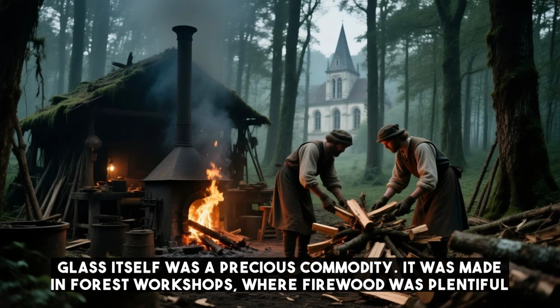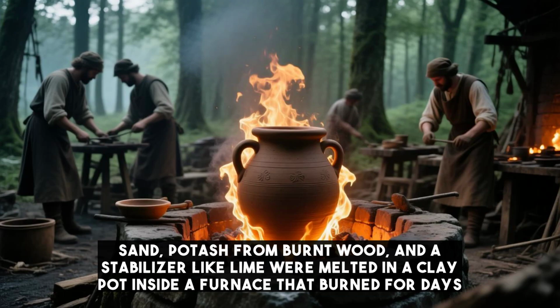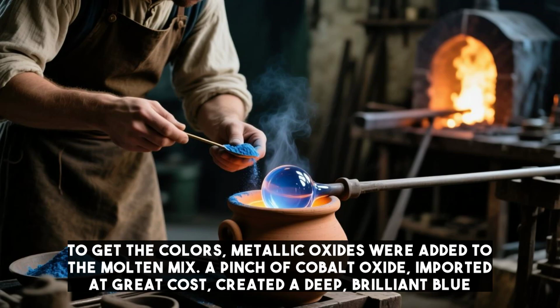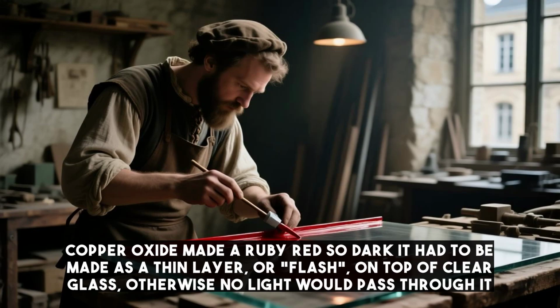Glass itself was a precious commodity. It was made in forest workshops where firewood was plentiful. Sand, potash from burnt wood, and a stabilizer like lime were melted in a clay pot inside a furnace that burned for days. To get the colors, metallic oxides were added to the molten mix. A pinch of cobalt oxide, imported at great cost, created a deep, brilliant blue. Copper oxide made a ruby red so dark it had to be made as a thin layer, or flash, on top of clear glass, otherwise no light would pass through it.